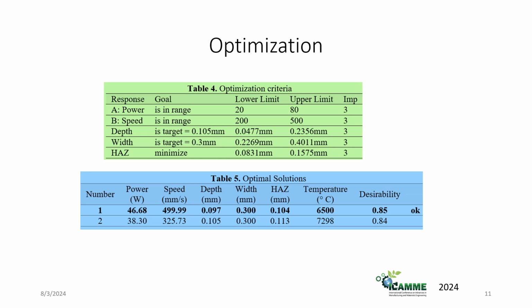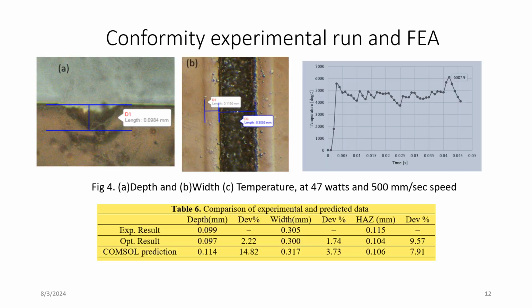Based on the highest desirability, 85%, a power of approximately 47 watt and 500 millimeter per second speed give our desired width and depth channel with a minimum heat affected zone of 104 micrometer. The confirmation experimental run was carried out at 47 watt and 500 millimeter per second speed. Results are shown in this figure.